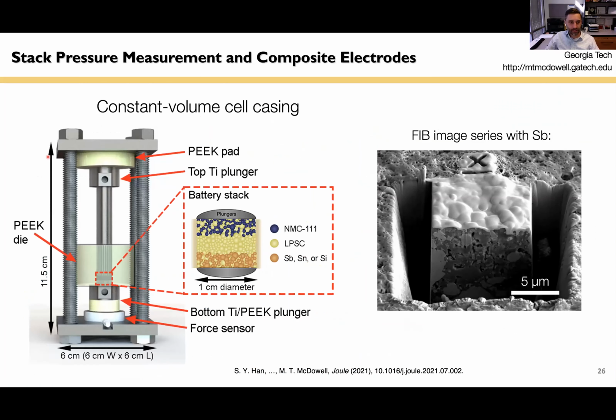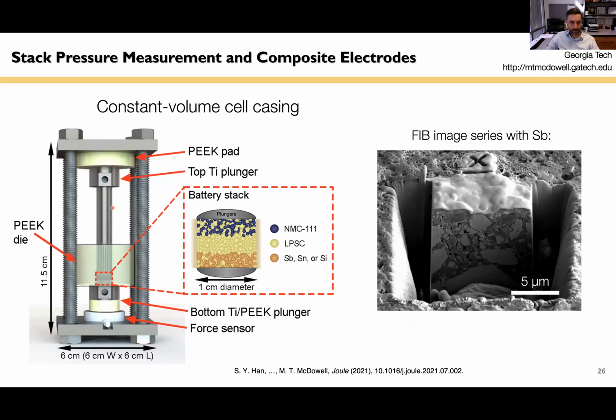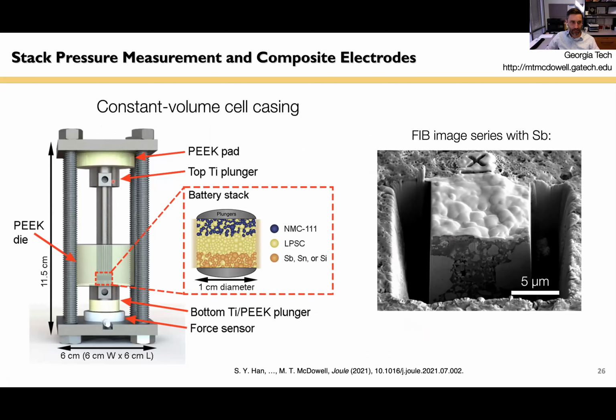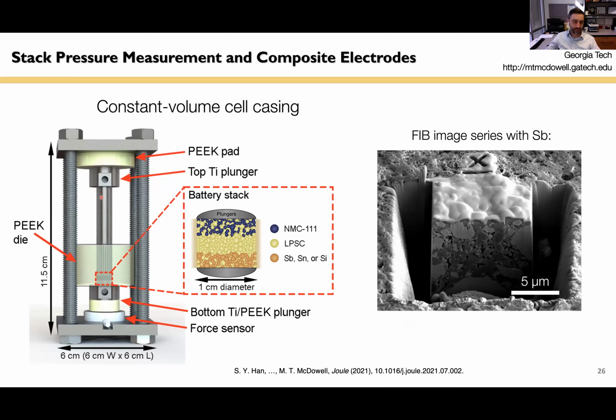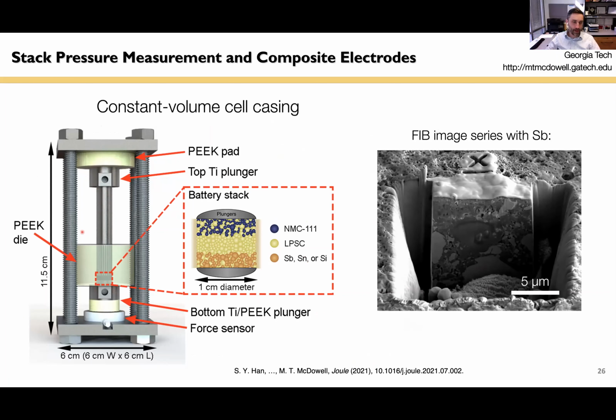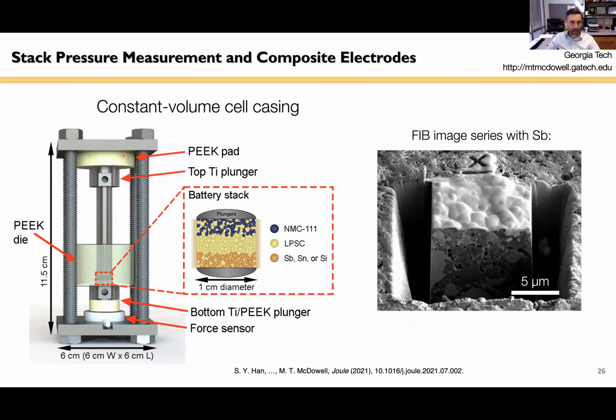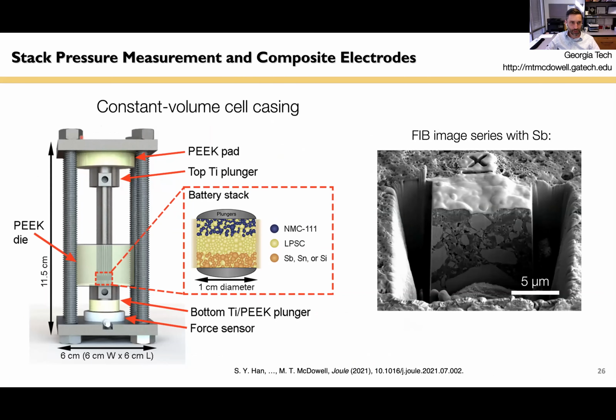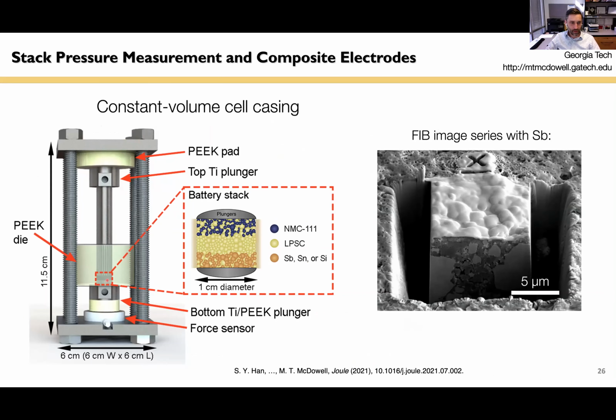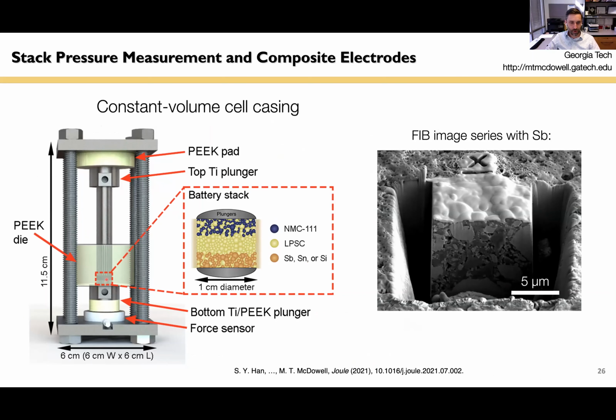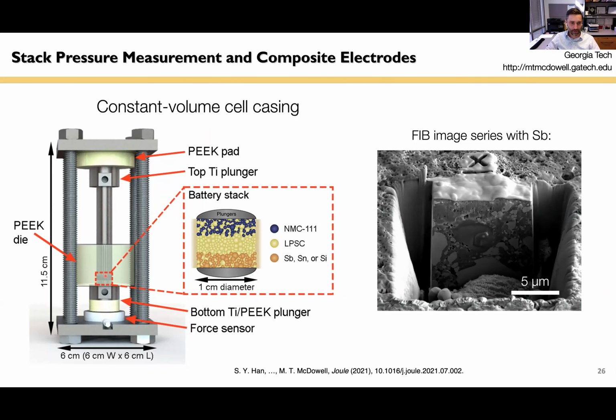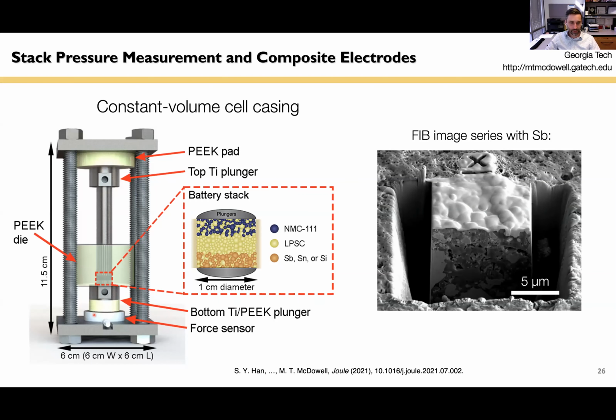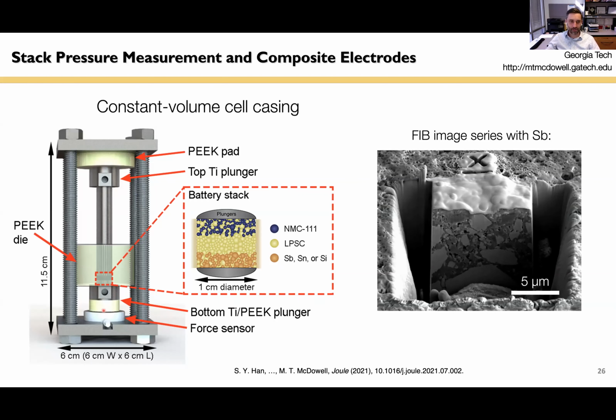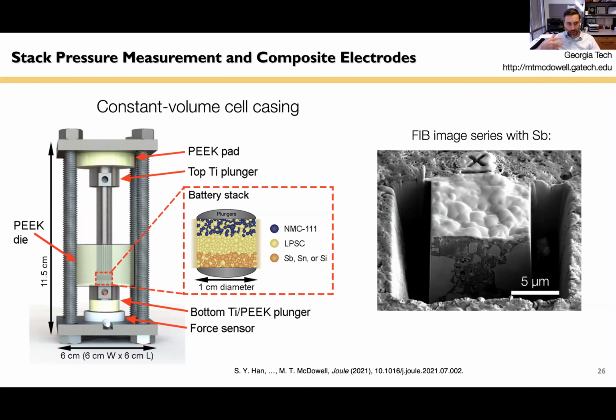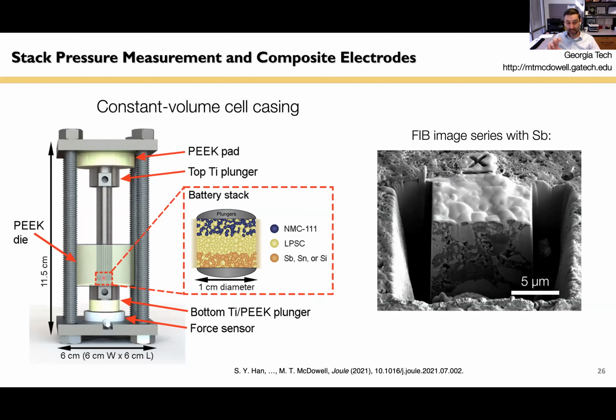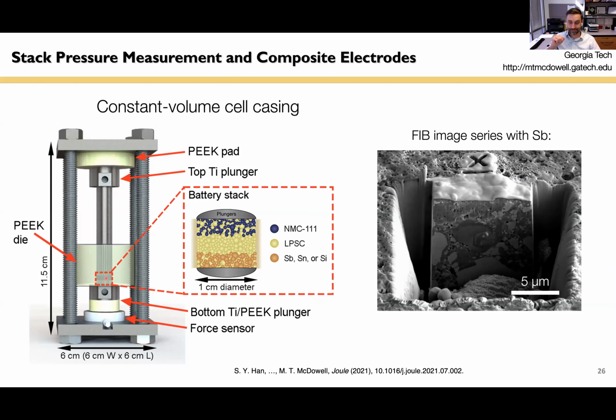So to do this, we built these custom cells here. There's a constant volume cell casing in these cells. You can see these look more like a uniaxial press than a solid state battery. But what this does is allow us to apply a controlled stack pressure with a torque wrench on these bolts up here. And then this is our very small battery stack down here, about 1 centimeter in diameter. And we also have a force sensor integrated into this stack, so we can measure the stack pressure that we're applying. And very importantly, we can also measure the stack pressure and how it changes when we cycle the battery. Turns out this is very important.